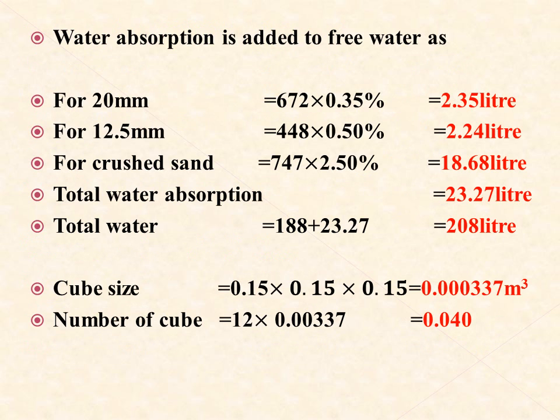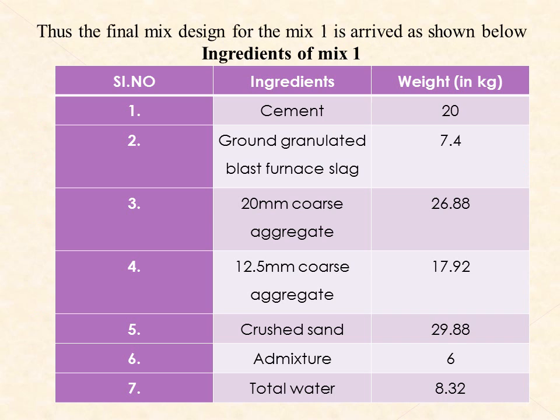It is multiplied, and water absorption is added to free water. So for 20 mm it is 2.35, for 12.5 mm 2.24, for crushed sand 18.68. Total water absorption is 23.27, total water 208, and the cube size is 15 cross 15 cross 15 centimeter. The number of cubes is 12, so the volume is 0.040 cubic meter. This is the final mix for ingredient 1, that is for 100% PPC.